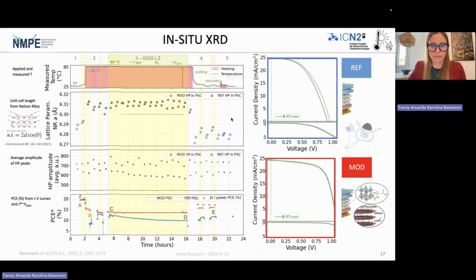Okay, so just to summarize, one of the most interesting things is that we didn't see any change in the lattice parameter over time at 85 degrees Celsius. So there does not seem to be any evolution over time of the lattice parameter. However, we see this decrease in the reference cell that really goes well together with the decrease in efficiency of the cell.